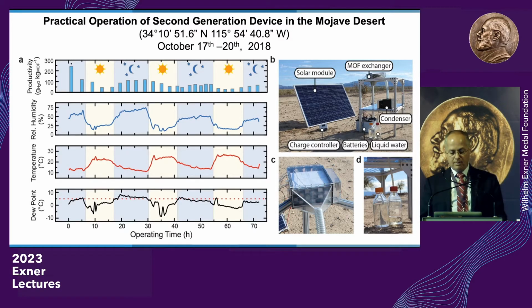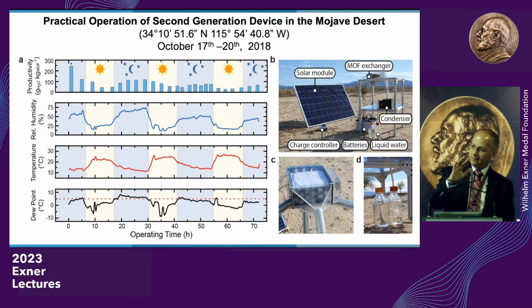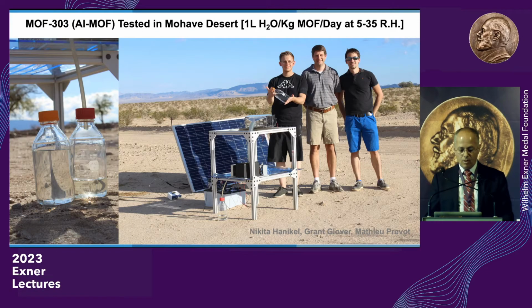And in this particular experiment, the students used a solar panel to provide power for a fan that pushes air into the MOF. Okay, so that you're not doing one cycle between day and night. So in fact, you push the air into the MOF, it takes up the water, and then as the MOF gets filled up, you heat up the MOF and then harvest the water. And you can repeat this. And so they delivered 1 liter of water per kilogram of MOF per day. Again, the material is not fully optimized, but still you have 1 liter of water per kilogram of MOF per day at really arid region humidities.